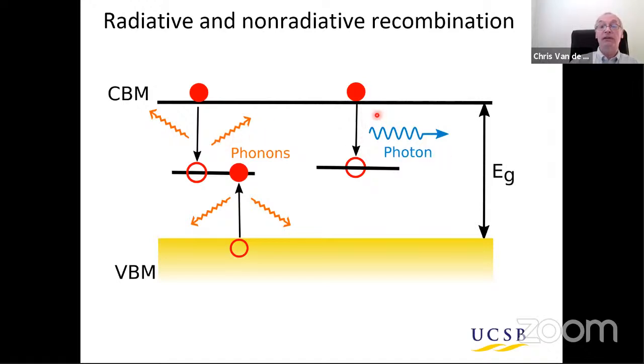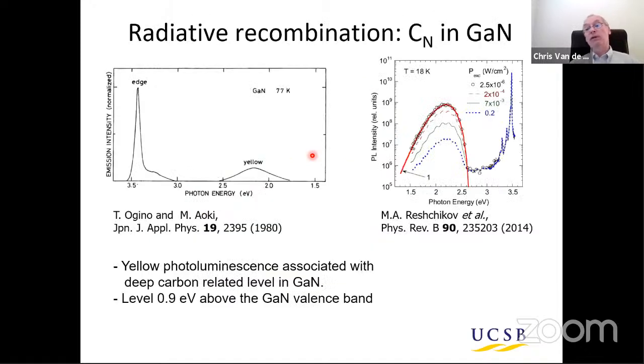Okay. As I already mentioned, you can either have radiative or non-radiative recombination. This is illustrated here with the example where you would have a defect level in the band gap that can have different charge states. You have, for instance, electrons in the conduction band. Those electrons can lose energy by going to an empty state in the defect level, and the energy can be lost in terms of emitting a photon or through lattice vibrations, phonons. Let's first talk a little bit about radiative recombination.